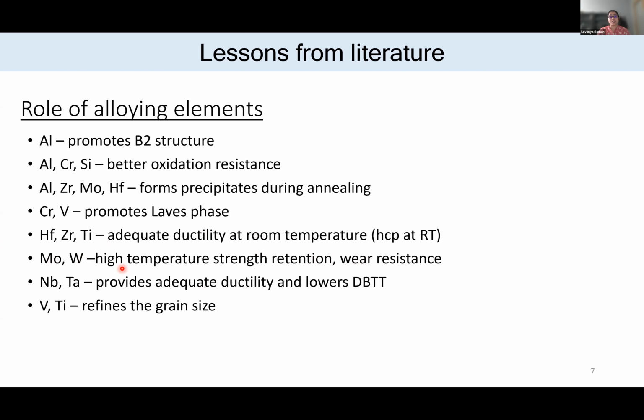So finally, when we need an alloy with adequate ductility and toughness, we'll have to add elements like niobium and tantalum. And some studies have shown that the addition of vanadium and titanium helps in refining the grain size. So these are the things which we can get from the literature. Now we'll have to design an alloy which will have an optimum combination of everything in terms of density, ductility, strength, and thermal stability.